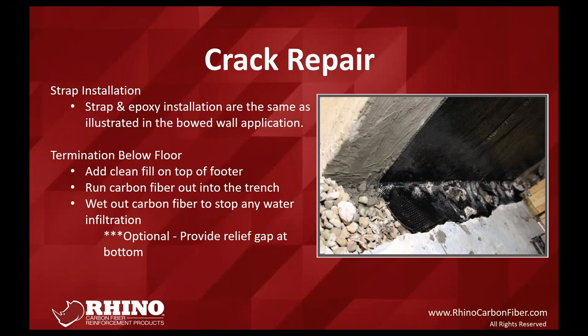So the crack repair is adaptable to be used for water control. If you're going to use it for water control, you do have to remove a small section of the slab. The idea here is you're structurally reinforcing that crack, but you're also creating a waterproof barrier. So any water that enters that crack is diverted below the slab and then released from the footer. You have to remove a small section of the concrete, add some clean gravel in, and then do your carbon fiber application. Basically, the water hits the back of the material, it's forced down, and then it's released into the gravel and then over to the sump pump or the drainage system.